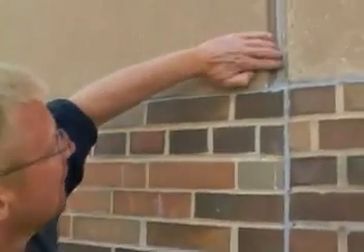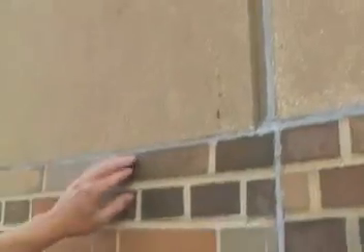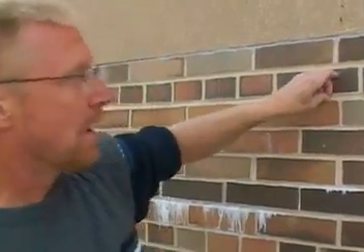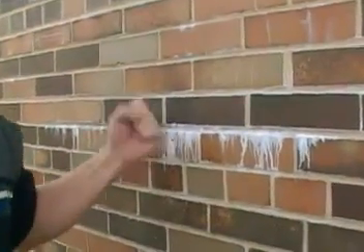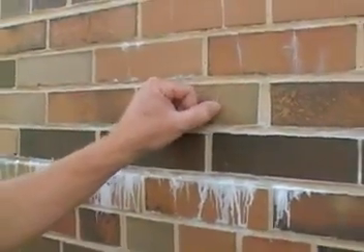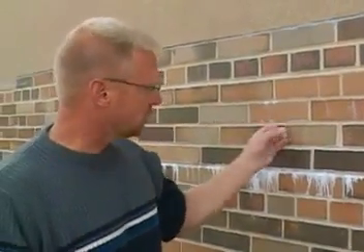You know, moisture truly is the masonry building's worst enemy, especially a building in need of work like this. As you can see, the control joints have failed, the caulk is separating from this precast concrete and allowing moisture to get in. The mortar joints are also showing signs of deterioration and need of tuck pointing. And also, we have another condition here called efflorescence, where the salts inside the masonry are actually dissolving and working their way out of the building because of the moisture within. Now what happens here is fissures get created inside the brick, and sooner or later delamination will occur, or spalling, where the surface of the brick will actually begin to pop off.